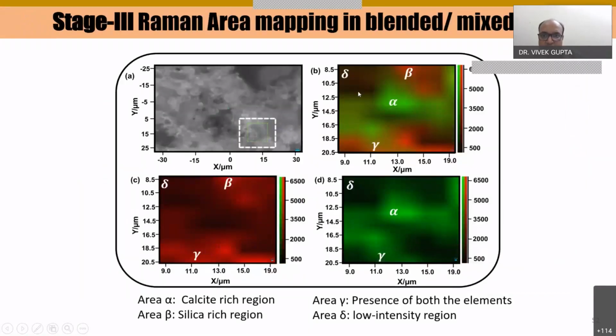Then we blended them, and we found that we were able to identify the individual ingredients in image form. Alpha is showing the calcite rich region, and beta is showing the silica rich region, and in the C and D images you can see the filtered image. And as I explained in the initial slide, if we are able to identify the individual ingredients at the microscopic level, we can say that if both the ingredients are present, the mixing is homogeneous. So we have taken multiple images at different locations, and in all the images we found the presence of both the materials, and we could identify both the materials at the microscopy level.